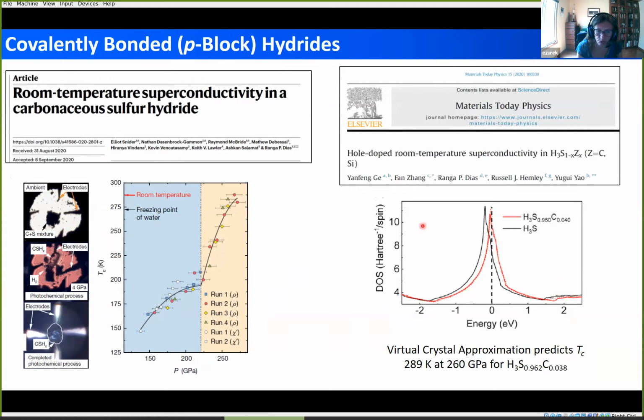So there was research published by Russ Hemley, Ranga Dias, Yanfeng Ge, that noted that there is this peak in the density of states near the Fermi level in the pure H3S. And if we could then just move the Fermi level to lie right on top of this peak, we would be able to increase the superconducting critical temperature of H3S.